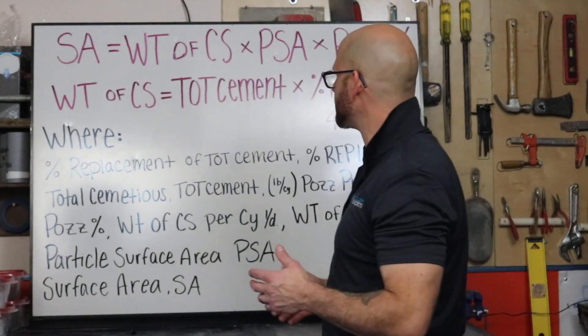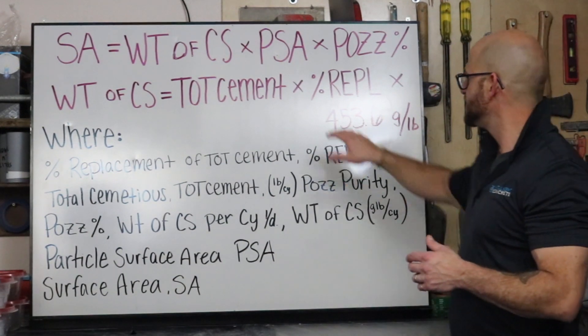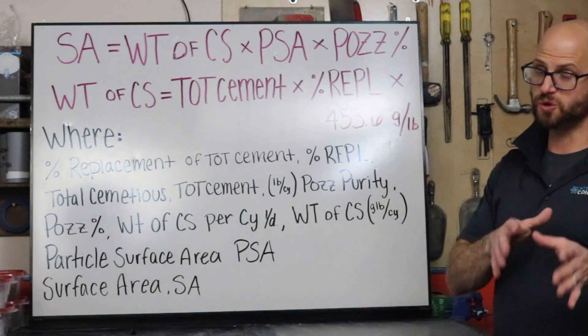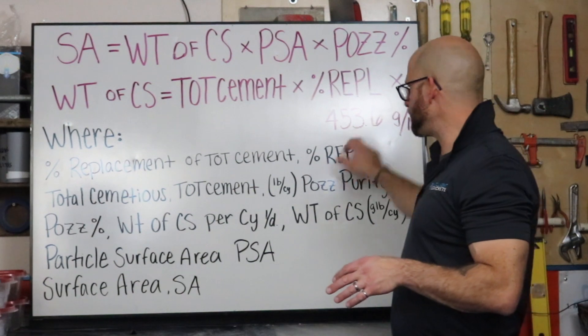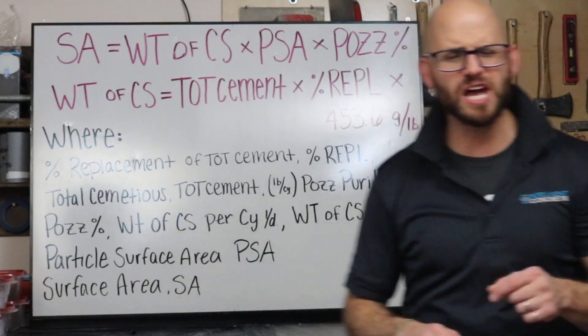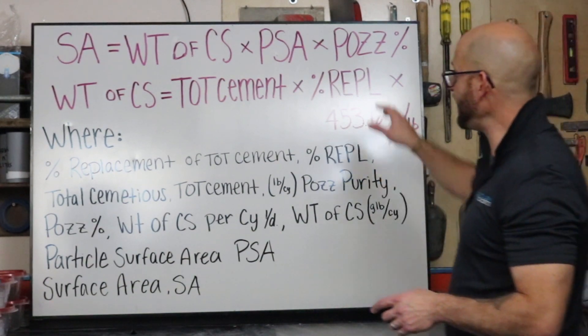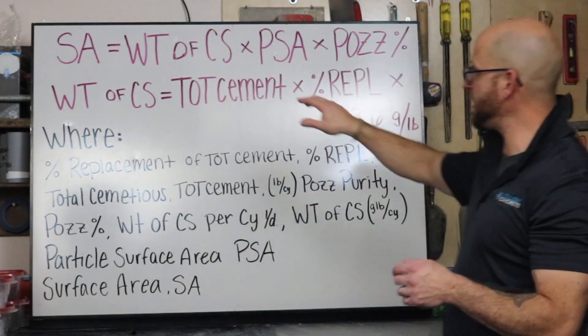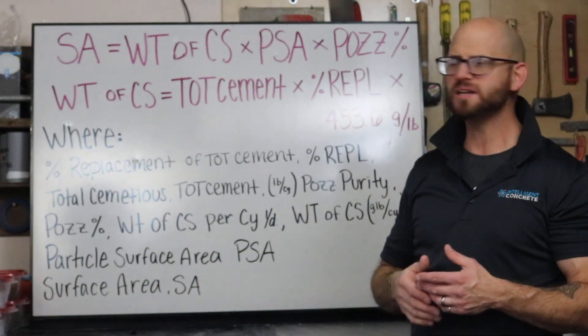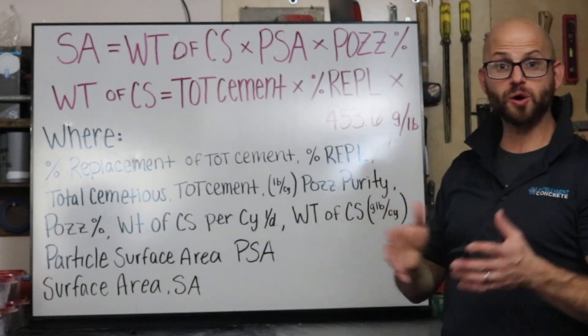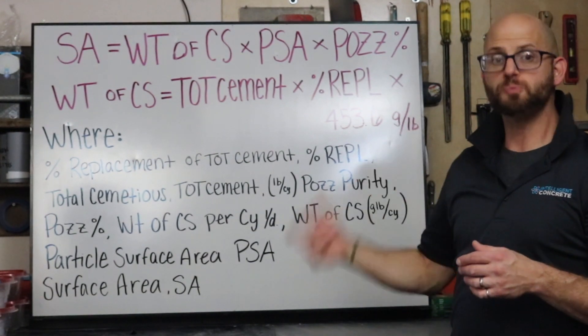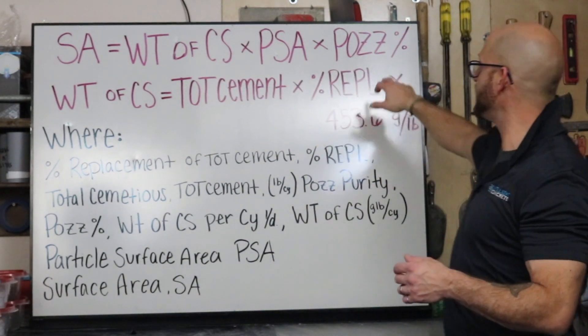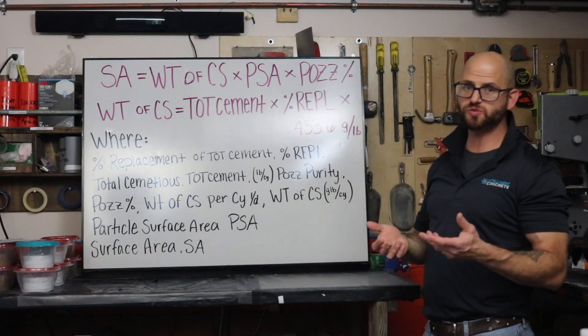To determine the dry weight of the colloidal silica, it's fairly easy: take your total cementitious and multiply it by the replacement percentage. That gives you pounds per cubic yard, assuming you're working in those units. Then multiply that by 453.6 grams per pound to convert to grams. Now back in the surface area equation, we have grams per cubic yard, which we multiply by the particle surface area in meters squared per gram — the grams cancel out — and we're left with meters squared.